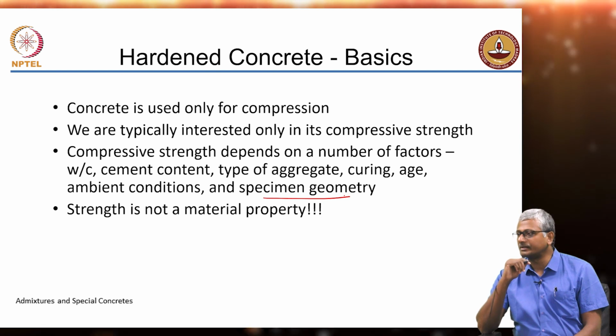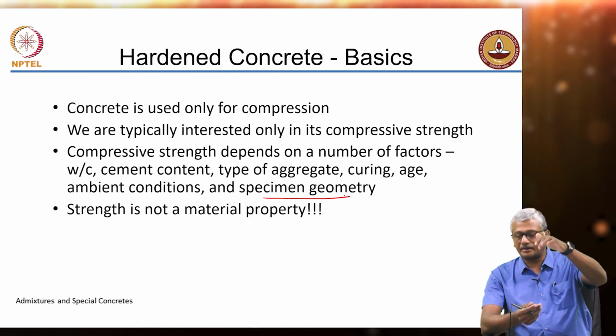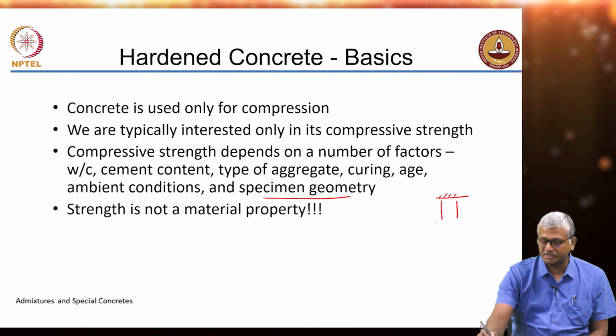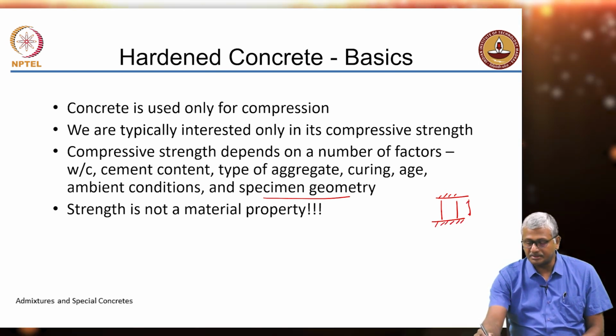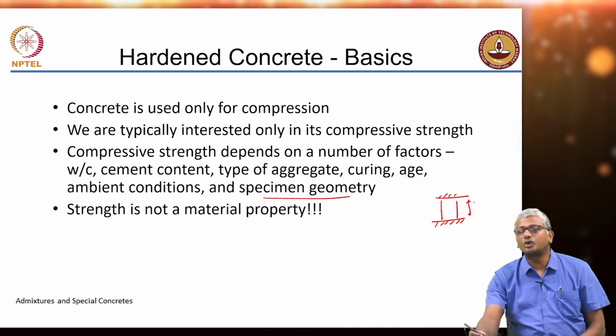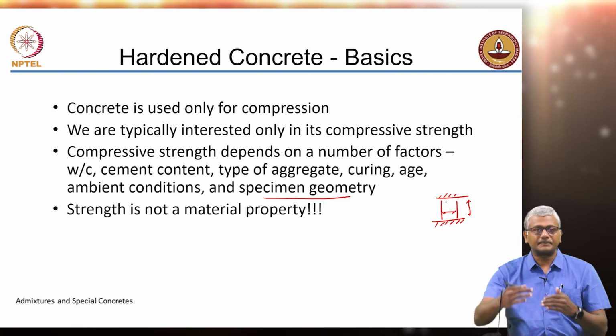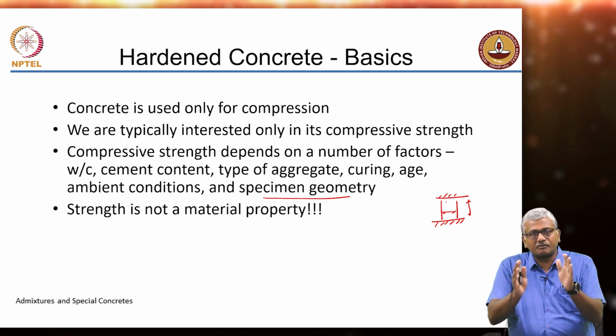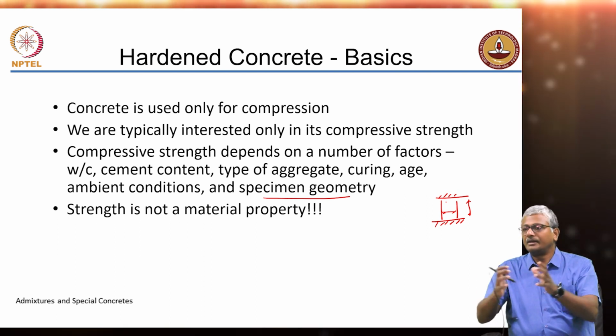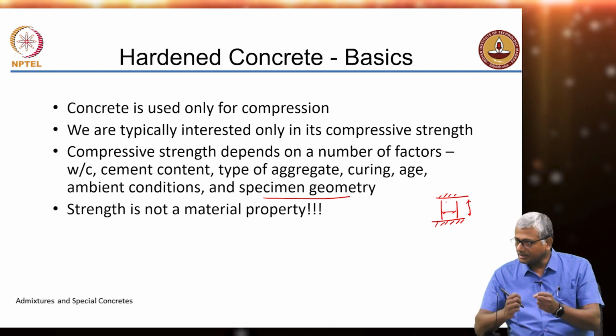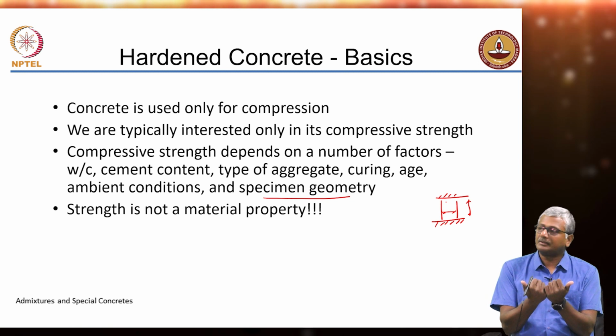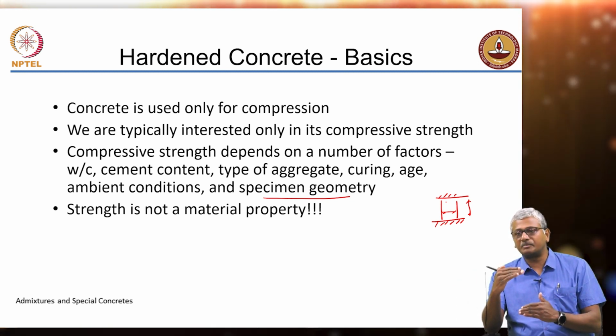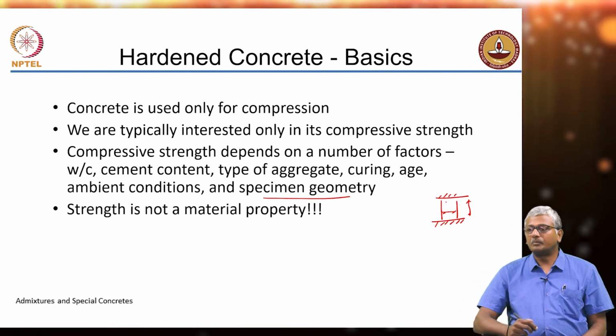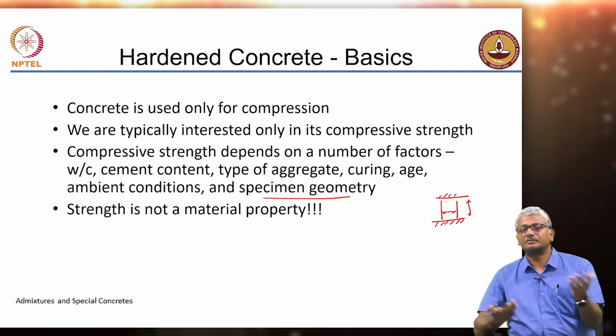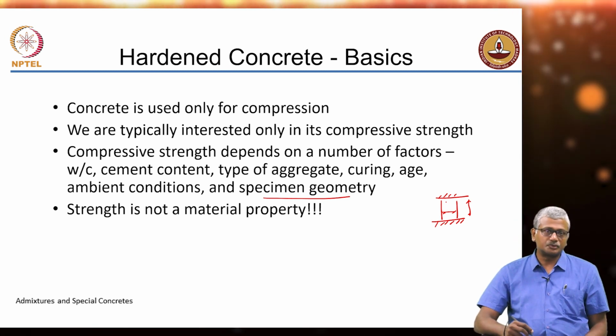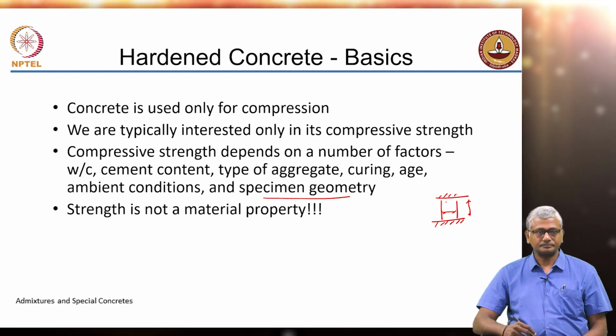So, why does cylinder then produce lesser strength than cube? You have a confinement effect of the end platens, right. You have the platens between which your specimen is getting loaded. If the specimen height or length is not too much more than the width, then the confinement effect is felt throughout the length of the specimen, and that confines the specimen from bulging outwards and cracking. So, how does concrete fail when you compress? It bulges outwards and cracks, right. Rather than crushing, it bulges outwards and cracks, because the tensile capacity in the lateral direction gets exceeded. So, when you have confinement because of the frictional effect of the platens, it restrains that bulging outwards, and because of which you end up with higher strength in cube, because the effective L by D in a cube is 1, in a cylinder it is 2. So, because of that you do not get any pure compression in the cube, right.